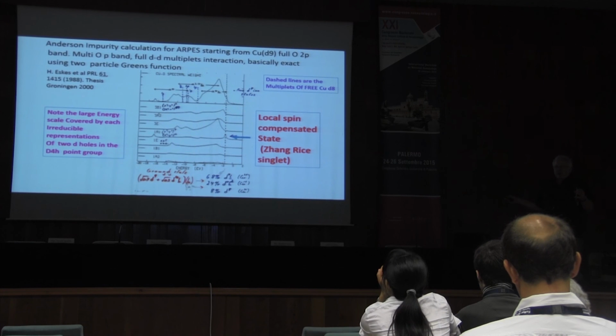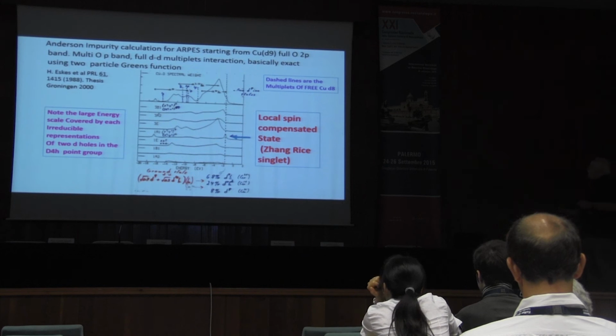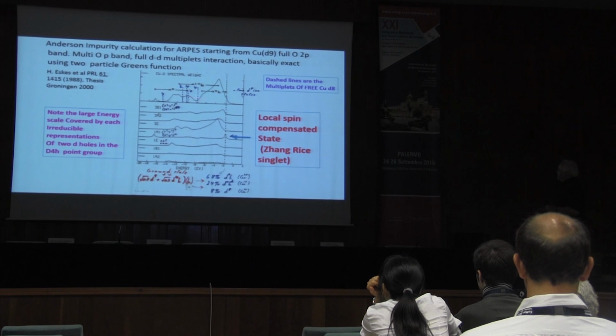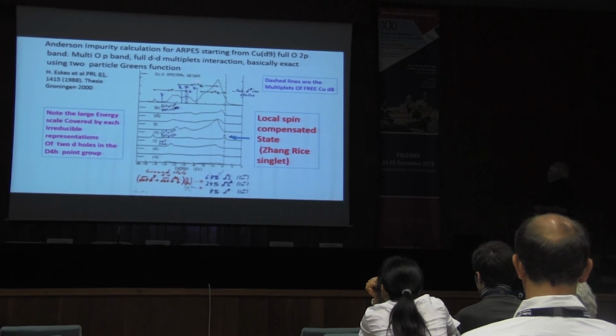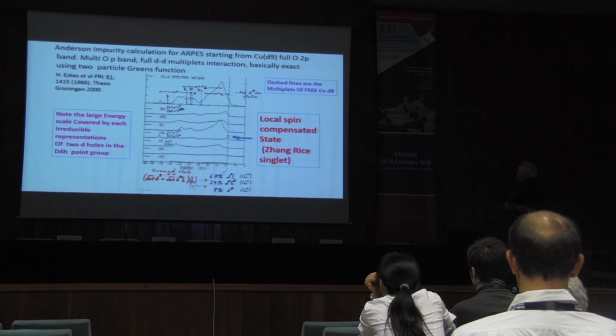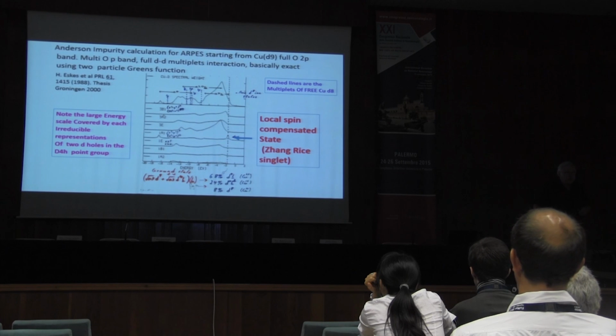Those multiplets actually spread out over 12 electron volts. You know, it's not a small energy scale. That's the reason why we have the beauty of Hund's rule and so on and so forth. Okay? So those multiplets would be all over here. So this is the electron removal part from the ground state, which is d9 and a full oxygen band. That was the assumption. Okay? So I look at the electron removal states. All I need to do is solve a 2-particle problem, which basically is the theory of Auger spectroscopy, but you could do it exactly.